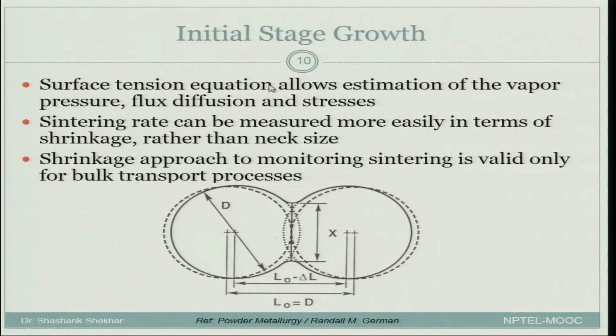But before we get over there, let us look at some more facts about initial stage growth. Surface tension equation allows estimation of the vapor pressure, flux diffusion and stresses. You can use surface tension equation that we saw for one of the cases and estimate the vapor pressure or flux diffusion and stresses. We saw an example of calculating compressive stresses. Sintering rate can be measured more easily in terms of shrinkage rather than neck size. So, neck size is a parameter which we use for densification, but that is not so easy to calculate. You will have to take very accurate micrographs. On the other hand, the parameter which is the interparticle distance, that can be much more easily calculated.